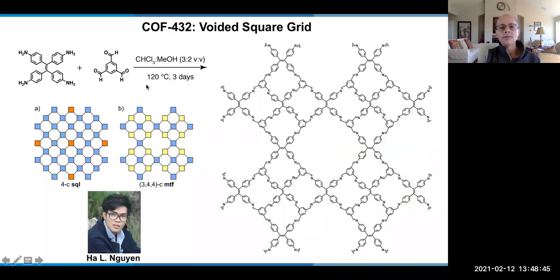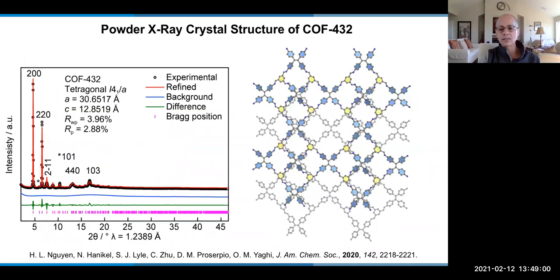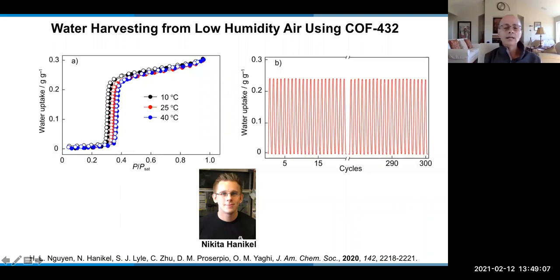This is another powerful example of how the orientation of the nitrogens around this unit, once we make the imine structure, makes a voided grid structure. And this turns out to be an extremely crystalline material, and to absorb water from air. In this case, the air is about 35 to 40% relative humidity, very similar to what you would get most of the year in a desert. But you see this beautiful step behavior, which is what you need for water harvesting from air. And that's done in a COF. You can see also here the reversibility of the uptake and release of water. The material is perfectly stable to water and to cycling the water.